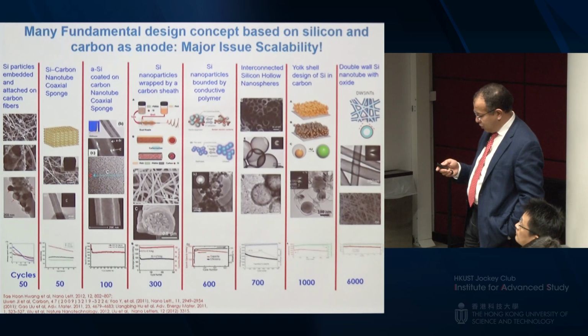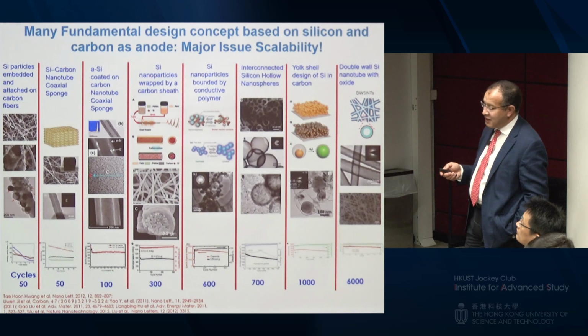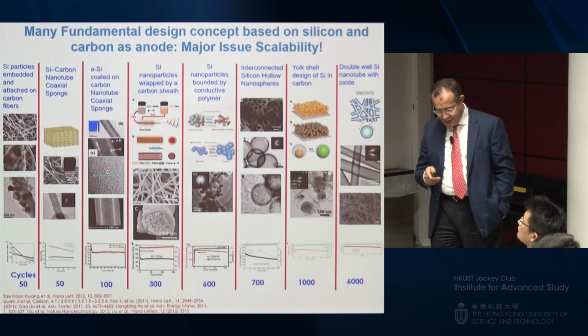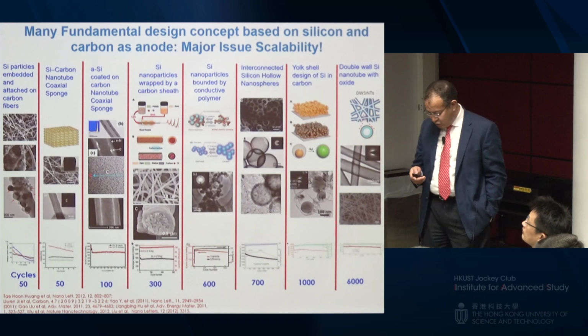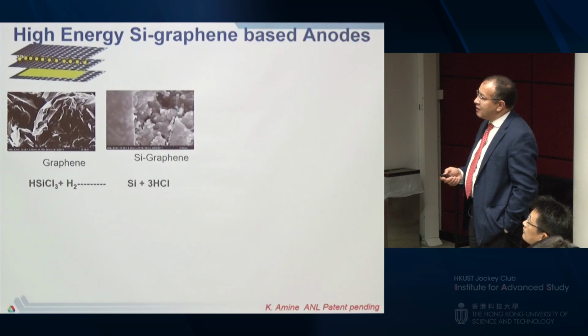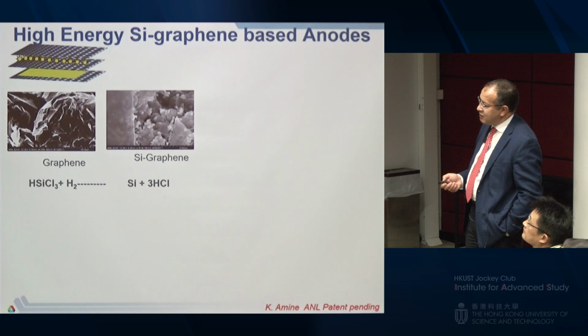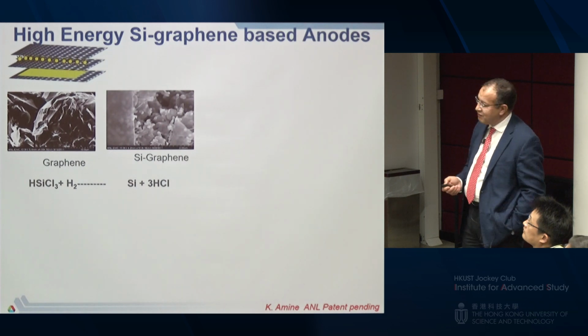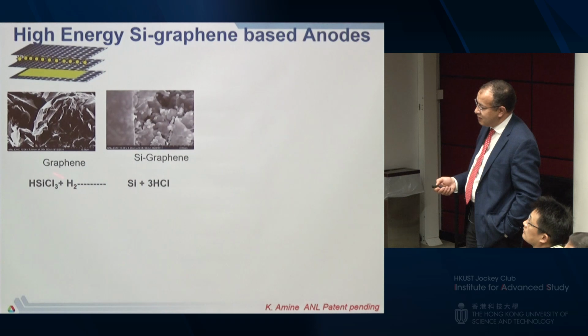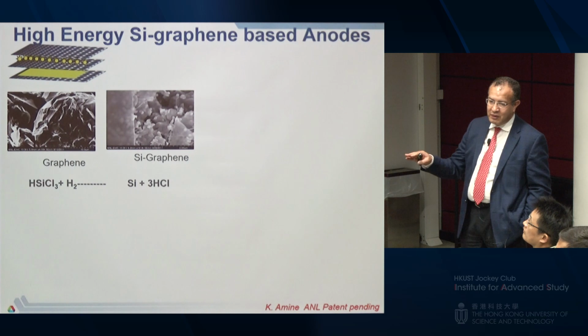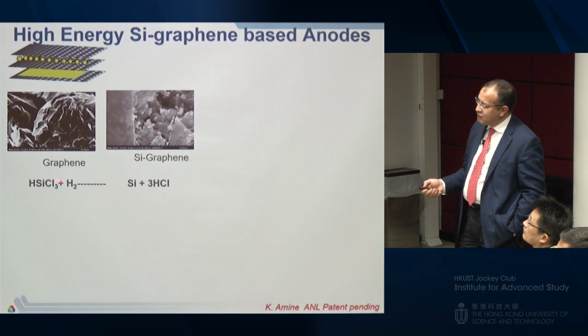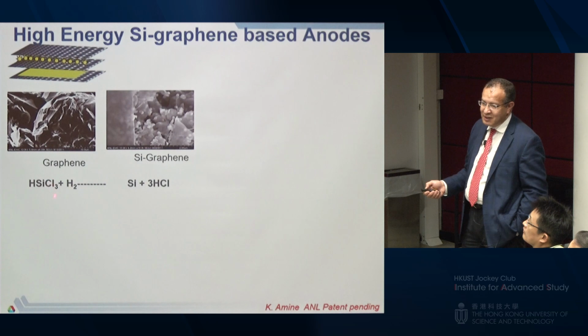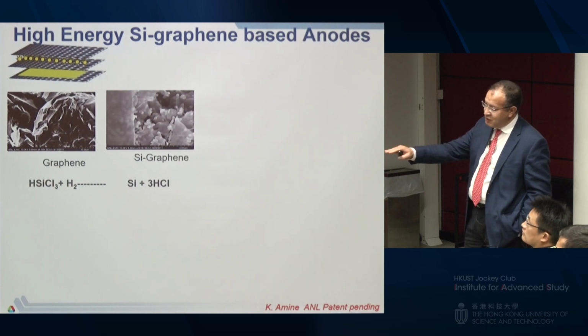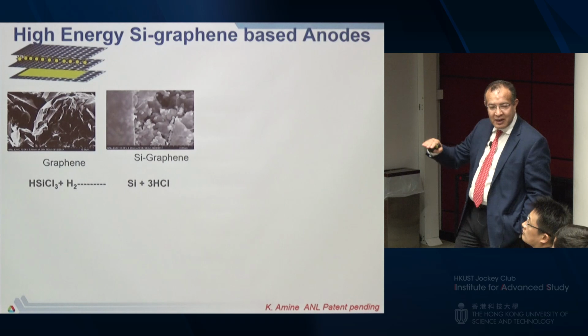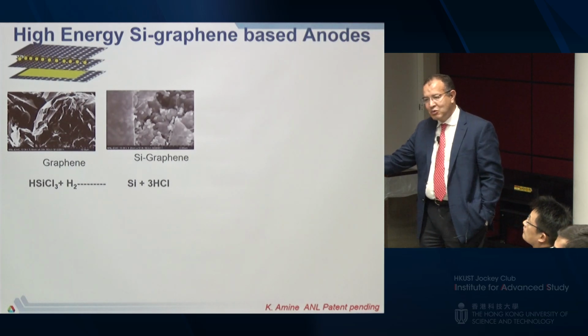So I'm going to show you an example of a new process that has been licensed and is in the process of being scaled up by a German company at the moment. The idea came when I visited a silicon wafer company in Silicon Valley, and we were talking about this concern. This is a very dangerous gas. That's the main source for making silicon wafer. They make thousands of tons of this material. The only problem is that when they send it to make silicon wafer, they contaminate it. And for silicon wafer, you have to have pure.